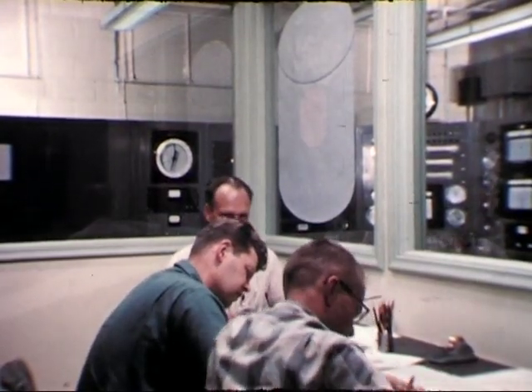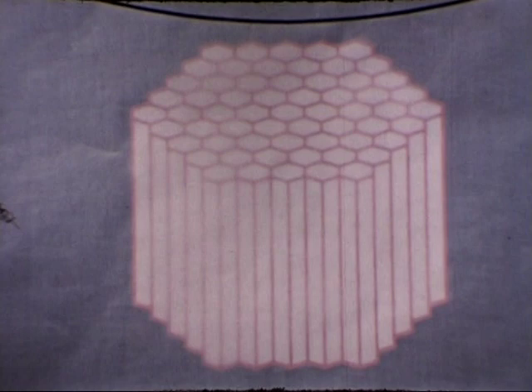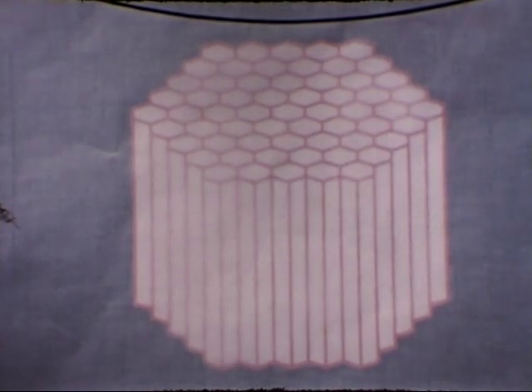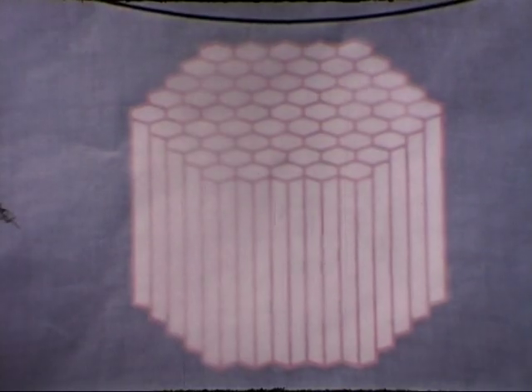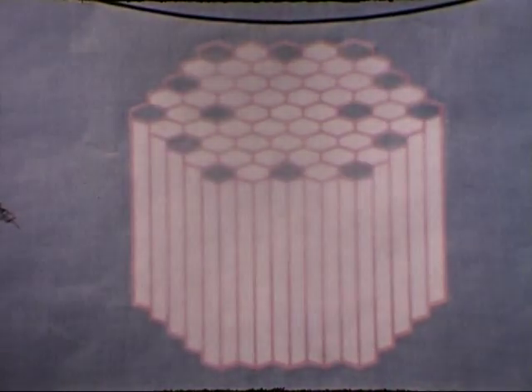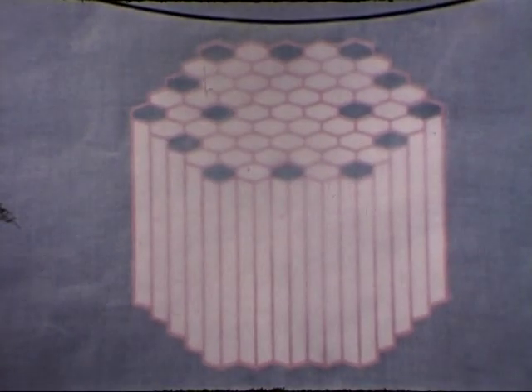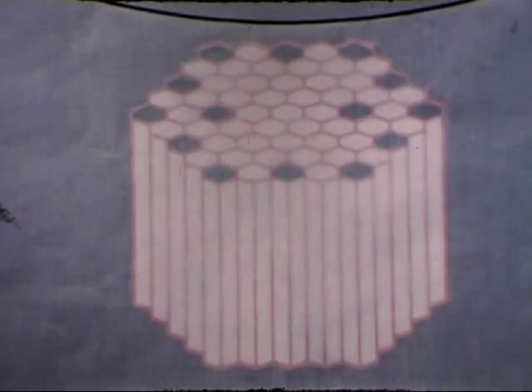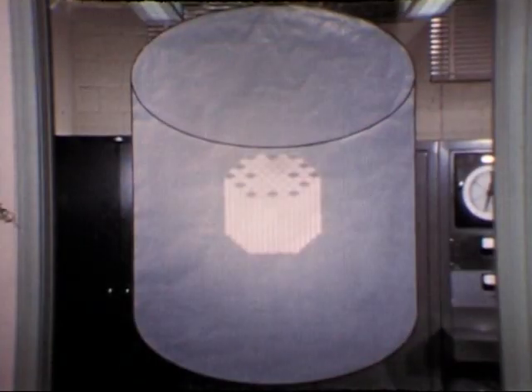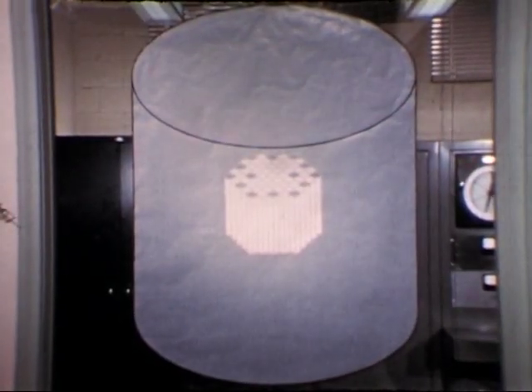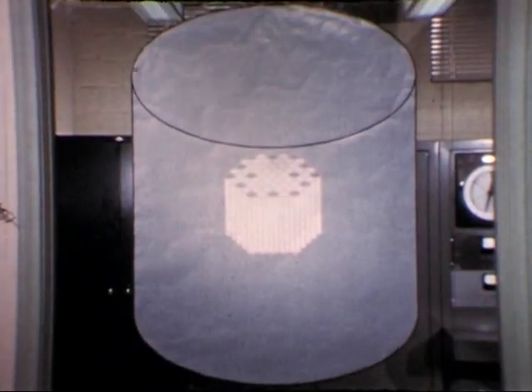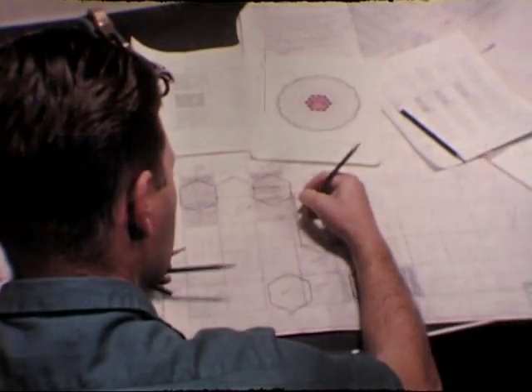The configuration and composition, as specified by the designers for EBR-2, is an enriched core having a height of 14 22/100 inches and a diameter of approximately 19 inches. The core contains 14 modified fuel subassemblies, which are utilized as control and safety rods. The enriched core is surrounded by a blanket having an outer diameter of approximately 61 inches and a height of 58 1/2 inches.